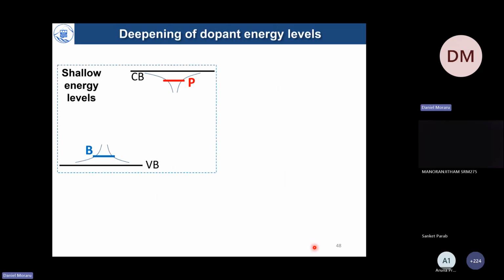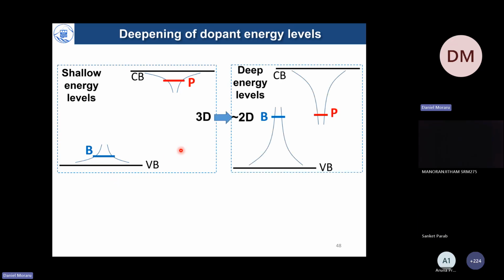First of all, what would happen if you have phosphorus and boron coupled together in a depletion layer? Basically, they are known as shallow dopants because the energy levels are only 45 millielectron volts from the respective bands. However, if you make it very thin, two-dimensional, even one-dimensional, the levels are deepened, and the phosphorus and boron can become pretty close to the mid-gap. In that way, phosphorus and boron, either single dopants or clusters of dopants, can introduce gap states.